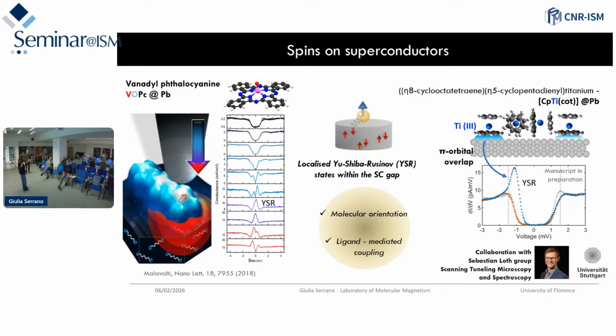So the combination of the ligand and the magnetic ion plays a big role in the surface interaction, I would say. And what is important depends on what you are doing. For example, when I spoke about the thick layer of iron 4 single molecule magnet on superconductor, there we were looking at a sensing mechanism, sensing the local field that extends for microns with respect to the surface. So we basically don't care what the single layer is doing. But when you have to really see the interaction between the single ion and the surface, you really need to control your single layer. I don't know if I answered the question. Yes.